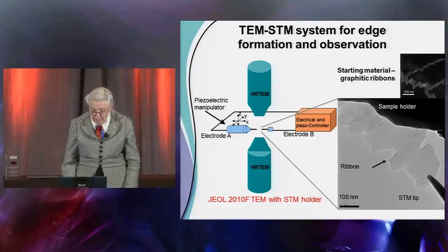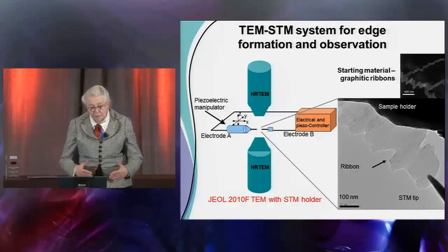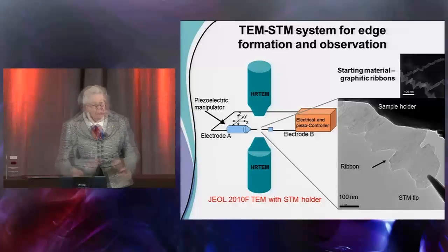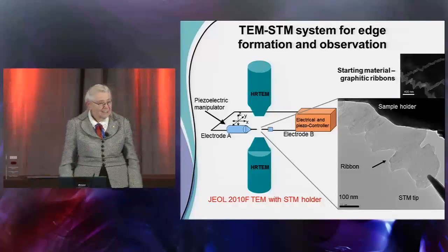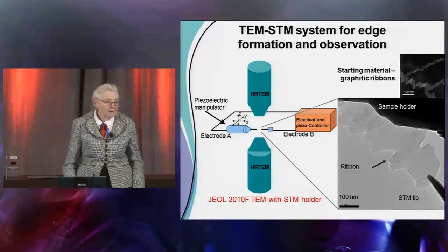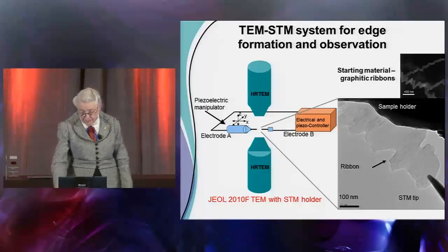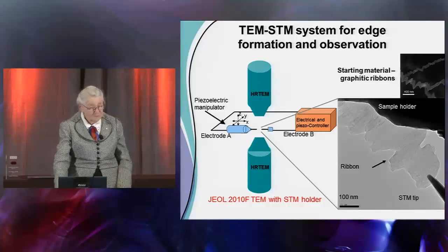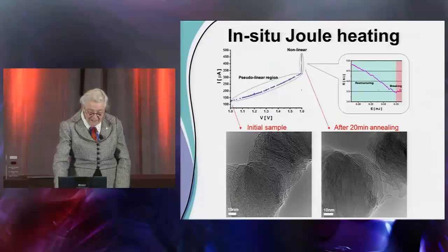So if you put a voltage across a ribbon like this, you can get pretty high current flowing. You can get heat generated. You have thermal energy transferred, and you can anneal a sample. And you can get to 2,000 degrees with carbon without working too hard in your laboratory, just IV characteristics.